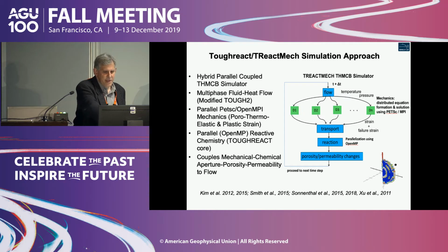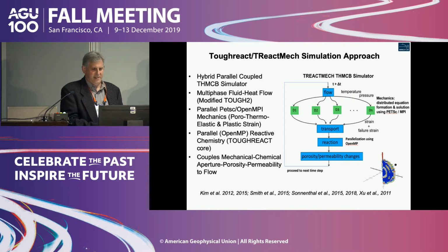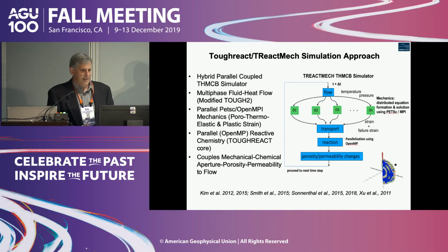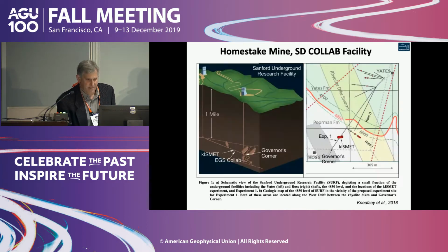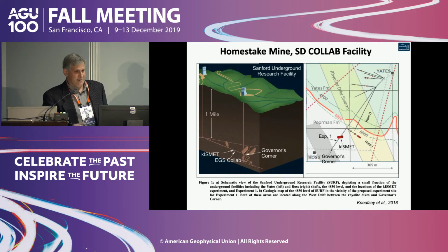And then we can transport all the species advectively and diffusively. Then we react minerals, aqueous species, gases, and so forth. And then all these processes are coupled to produce porosity changes. And then with various laws that you might use, you create permeability changes. Of course, all these have many uncertainties, but this is why you run a lot of simulations and you use a lot of alternative data to try to constrain the models. So this is all embedded in the TOUGHREACT and TOUGHREACT-Mech codes that we've been developing over a couple of decades, several decades now.